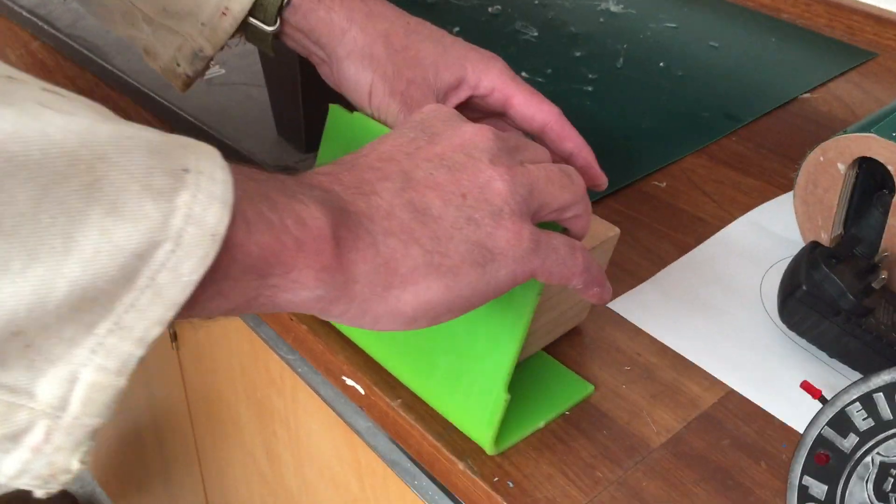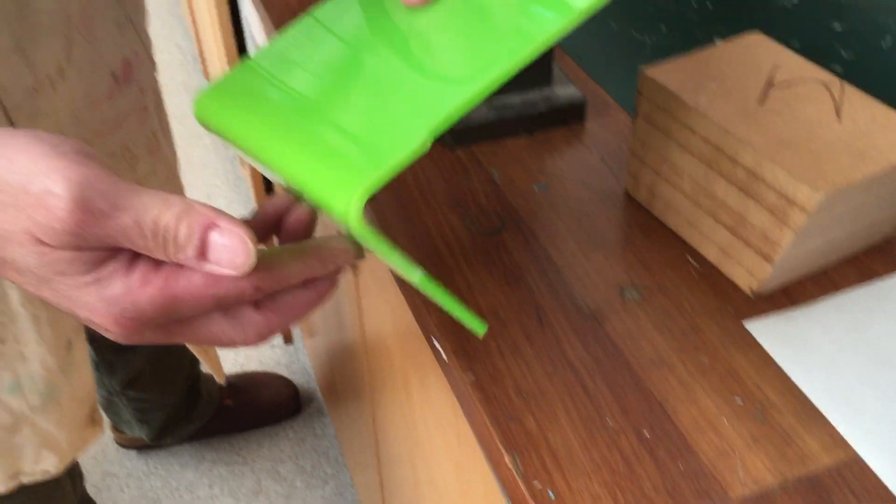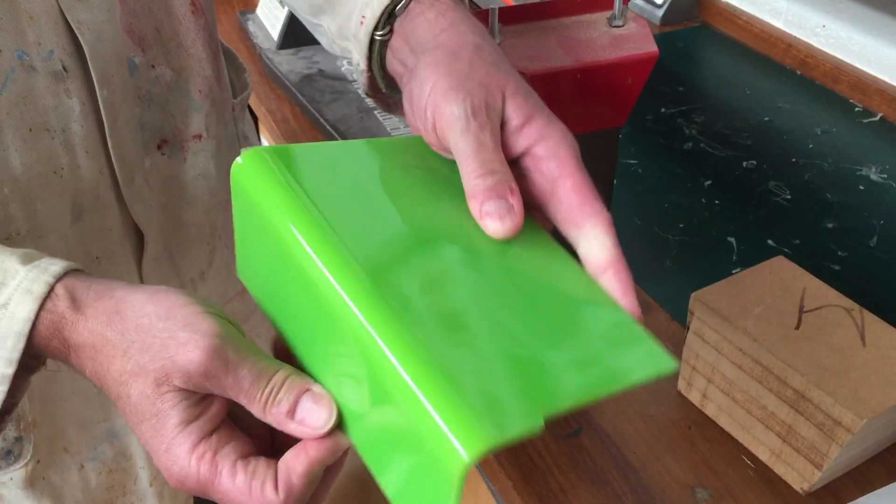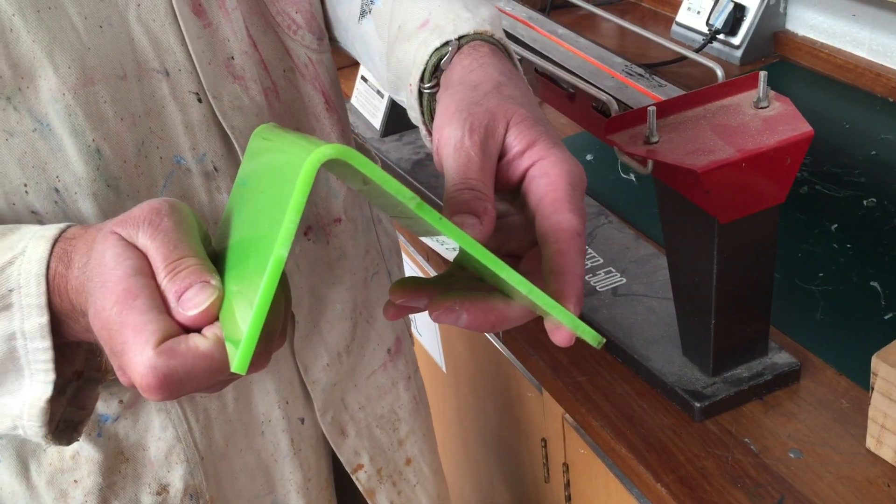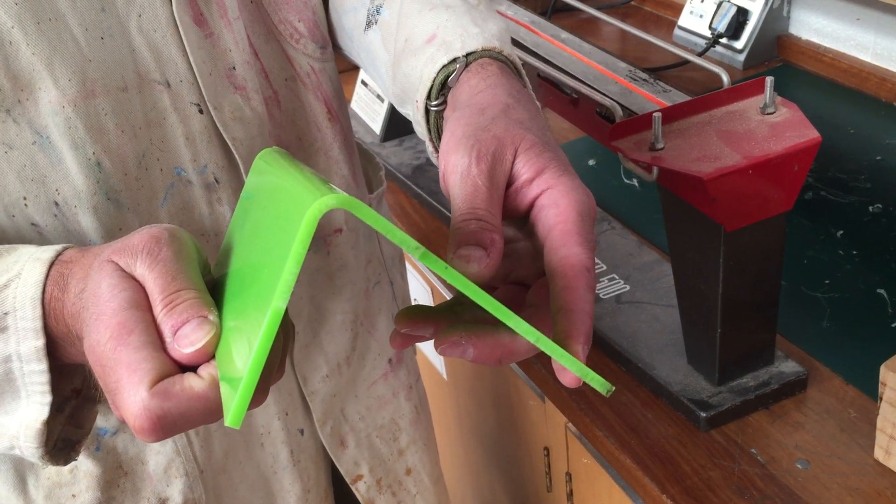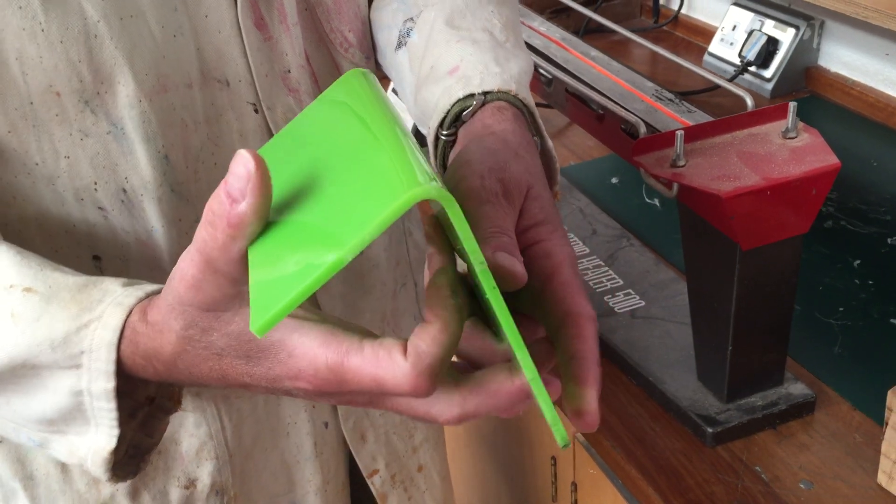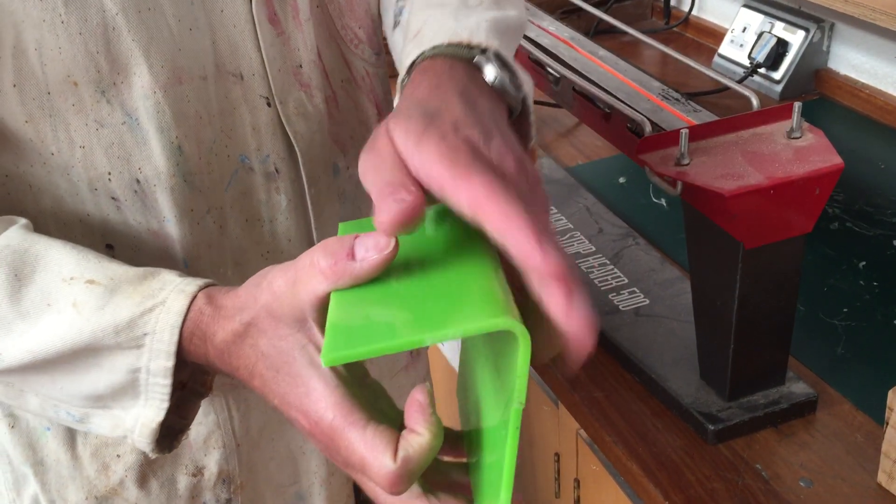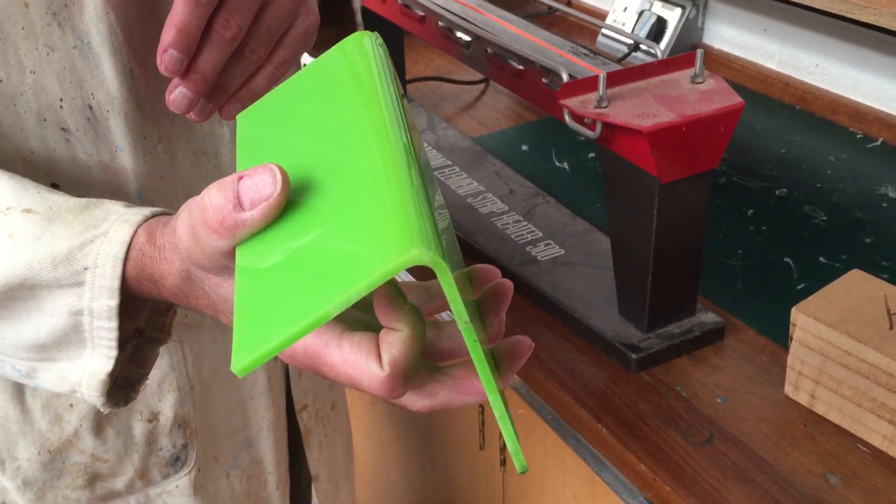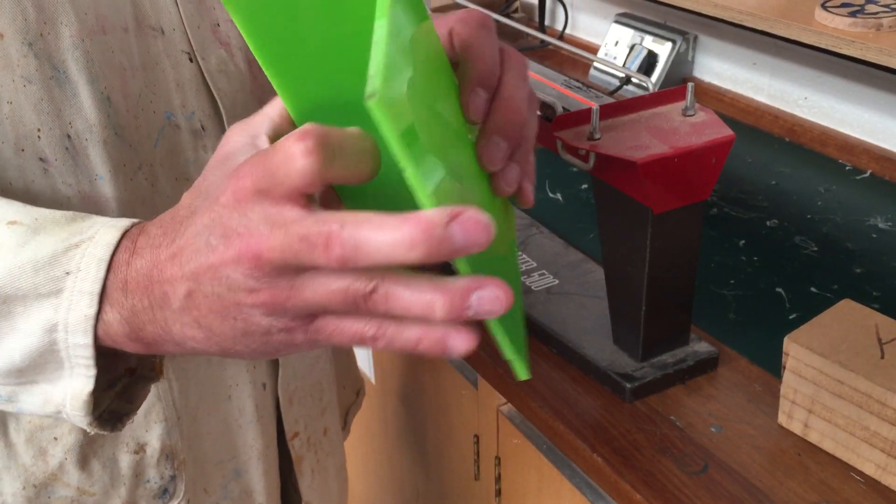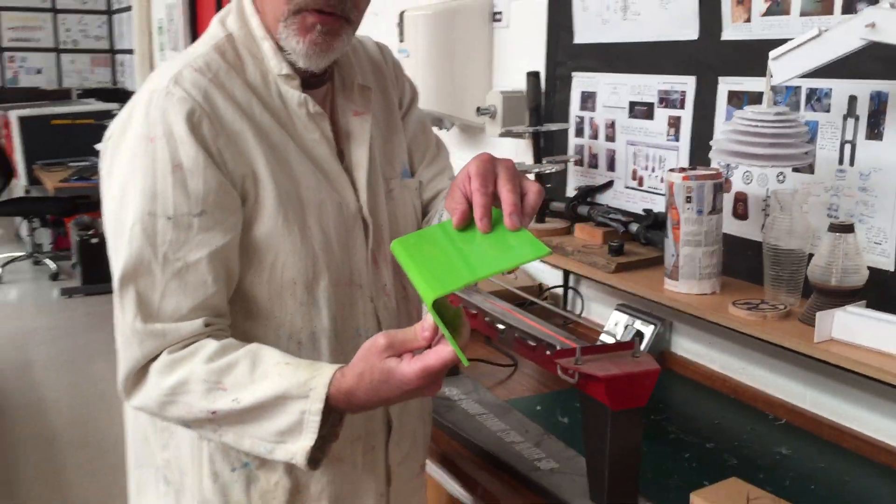Now it's been there for a minute or two. I've got the angle right, so I can take the jig away. I don't want to leave it because it will spring back slightly, so I'm just going to apply a little bit of pressure, keep that angle constant. And we can see if I was to let go, it would spring back slightly, and it's now getting cool enough to touch, but it's still quite hot. Yeah, I don't want to leave my hand on there, although it's not burning me. Okay, so that's the process of strip heating, sometimes called line bending.